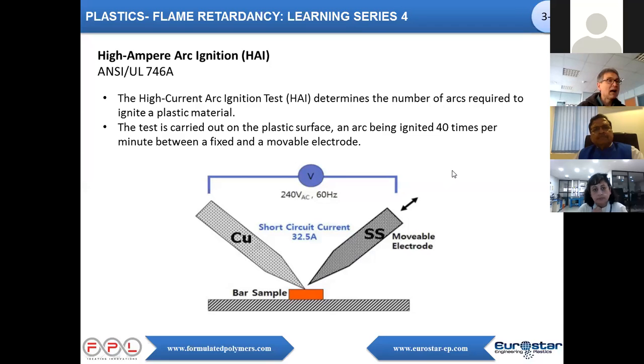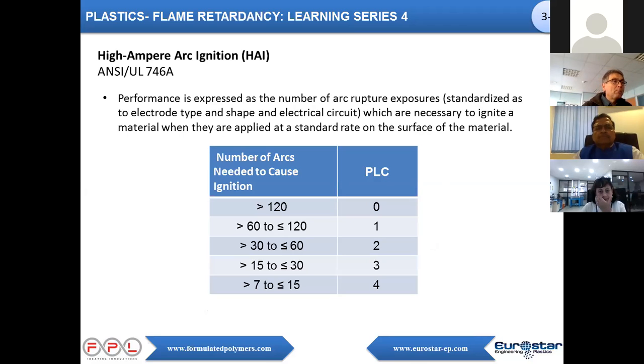Then another test is the high arc ignition. It's a bit different. The test, in fact, simulates the situation where an arc occurs between 2 electrodes under a low voltage but a high current, for example, 2 connectors spinning on a plug. The arc is created on the resin of a plastic, on the surface of the resin. So you have a fixed electrode, which is in copper, and a movable electrode, which is in stainless steel, under high current, and you are moving this electrode back and forth 40 times per minute to create an arc. And then you will have to see the number of arcs to ignition. And the same thing as previously, it is rated by a number of arcs,